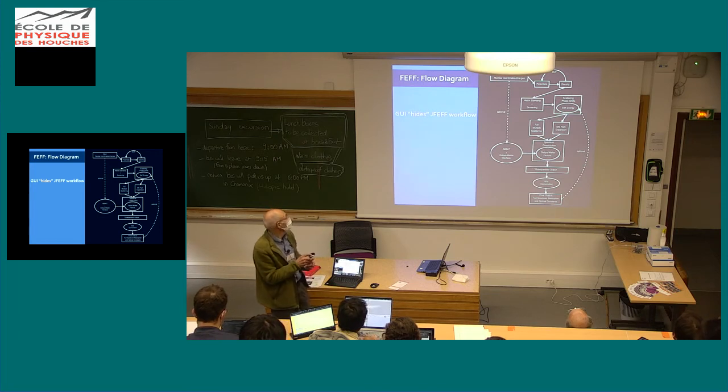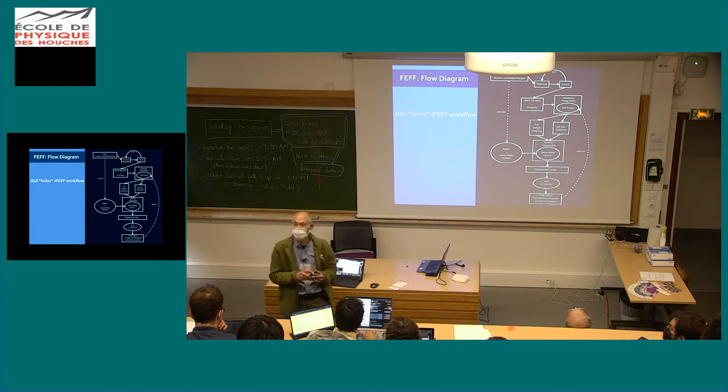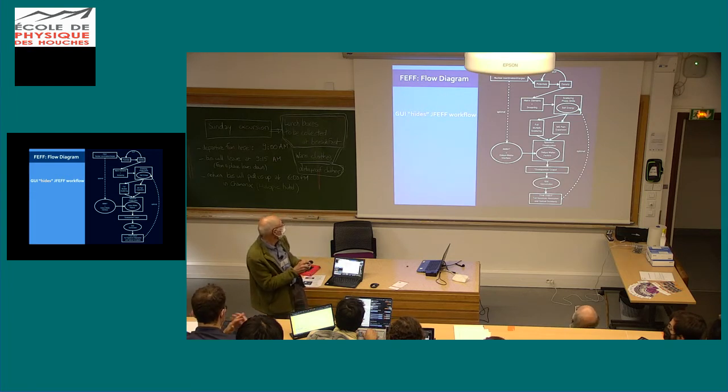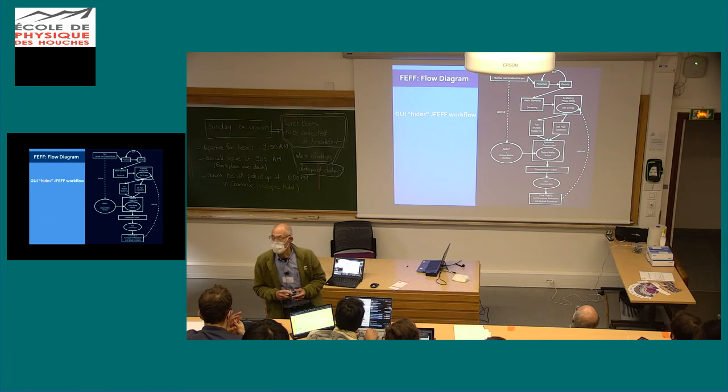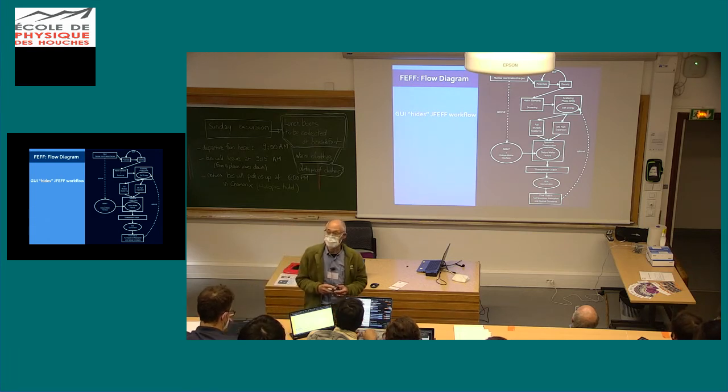Once we have that all converged, we calculate the potentials, then get some radial matrix elements and screening and scattering phase shifts, and then either do the full multiple scattering or the path expansion. Once we have that, we construct the spectrum, and then we put in Debye-Waller factors.